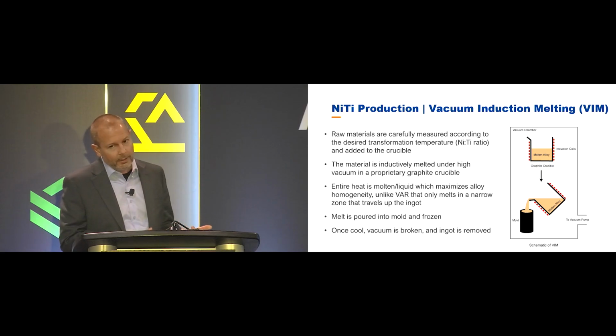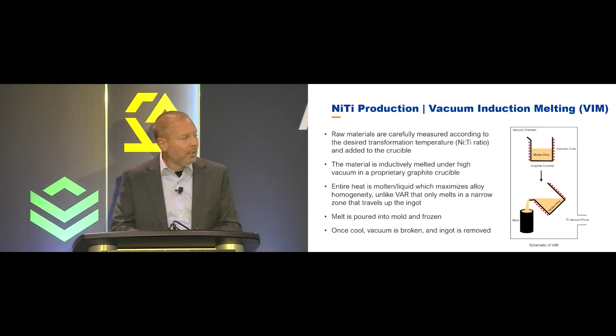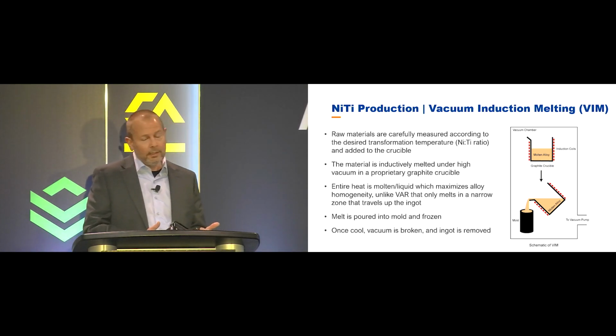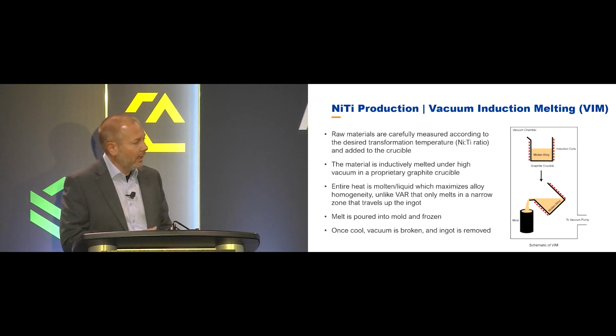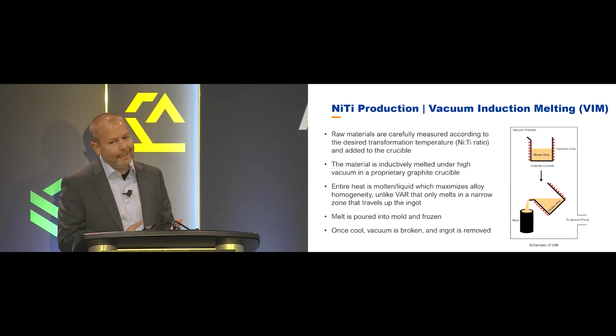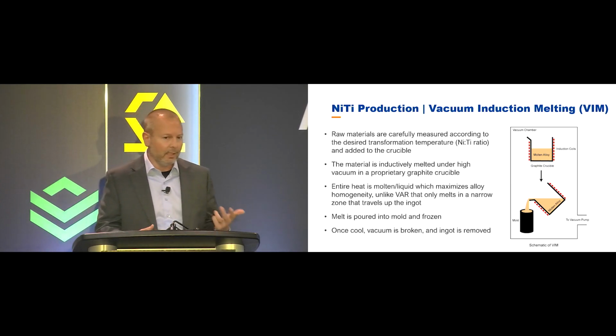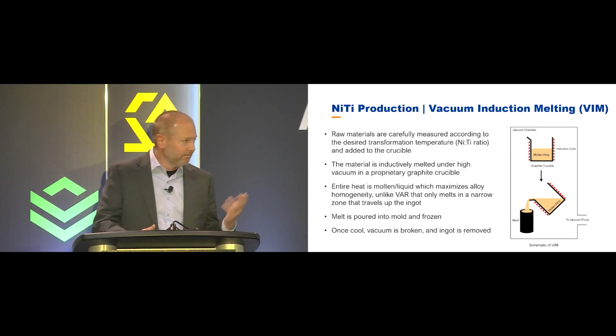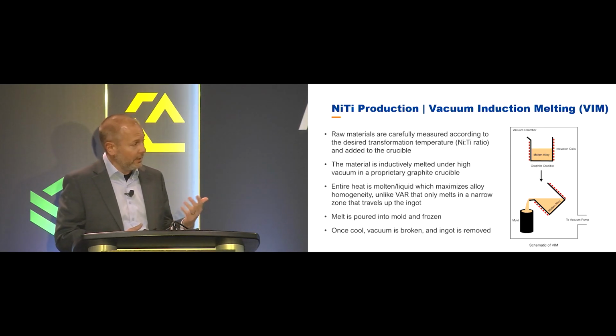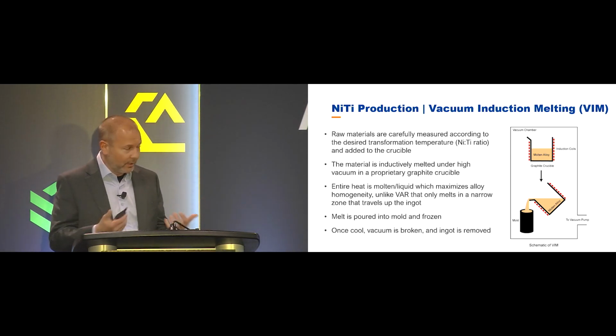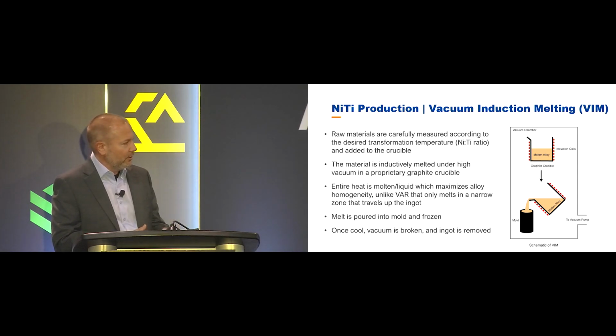Why do we use graphite? It has very good thermal shock resistance, and it's very resistant to degradation by the liquid nickel titanium. Liquid nickel titanium, the joke is it's the universal solvent. It will eat anything. If you try and use a crucible that's used for superalloys, an oxide, magnesia, alumina, zirconia, all you're going to end up with is nickel titanium oxygen. It will just suck up all that oxygen, and you might get 2 cycles to failure on your crucible.